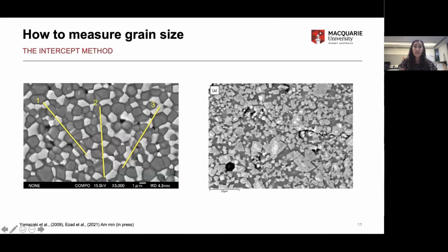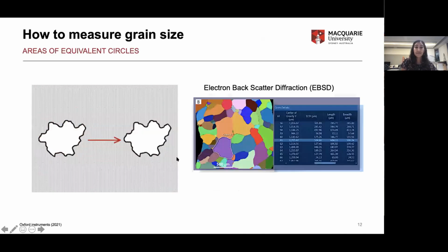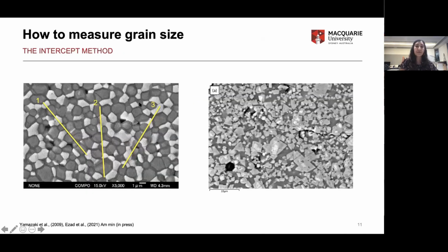The most common methods of measuring grain size are the intercept and the areas of equivalent circle. These techniques are so popular that within the last 5 years, the intercept method has been published 609 times in peer-reviewed journals. And it's a pretty simple and efficient method to measure grain size. The idea is you draw random straight lines everywhere in your sample, and you measure the number of intersections of grain boundaries with your line, and you know the length of this line because you have your scale bar,